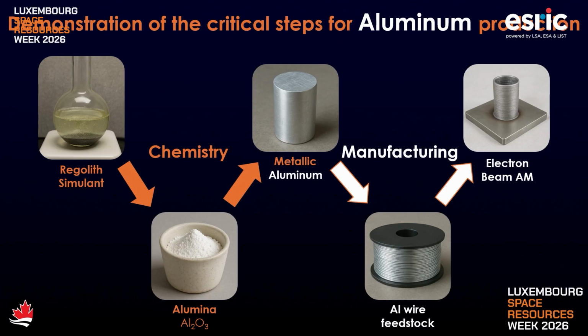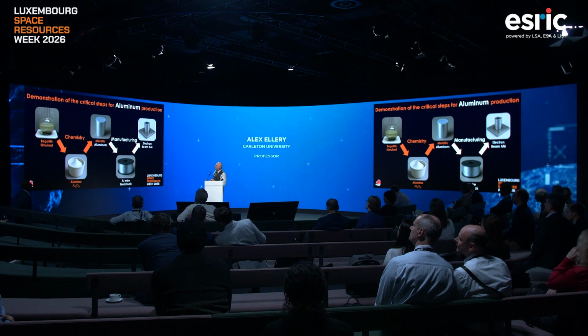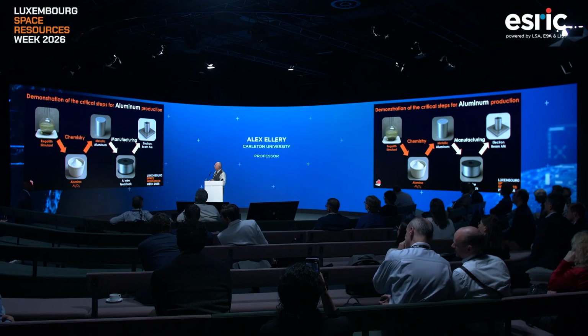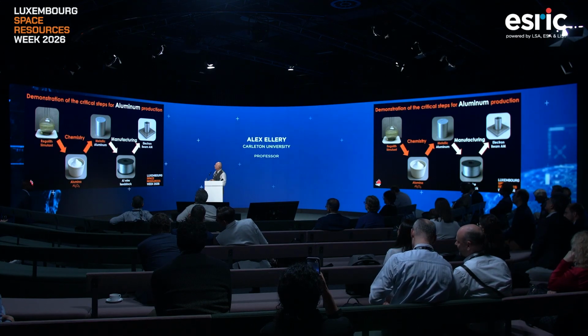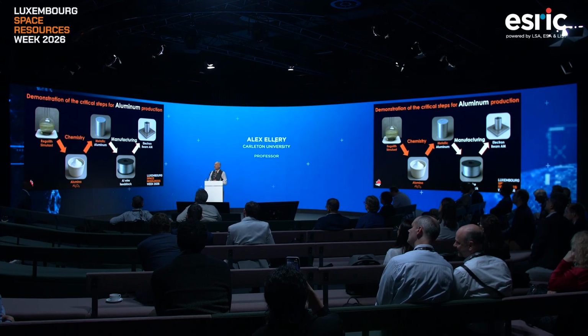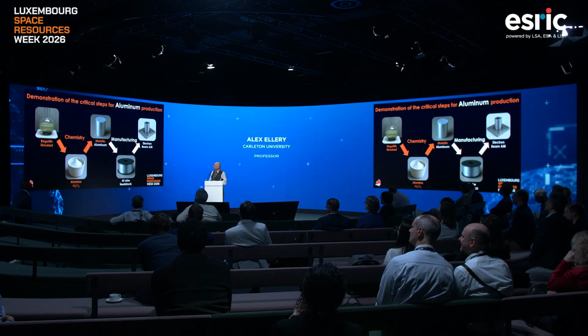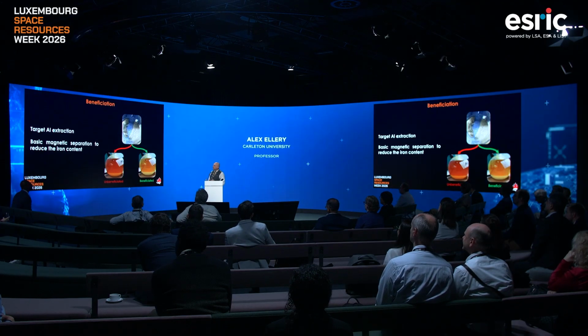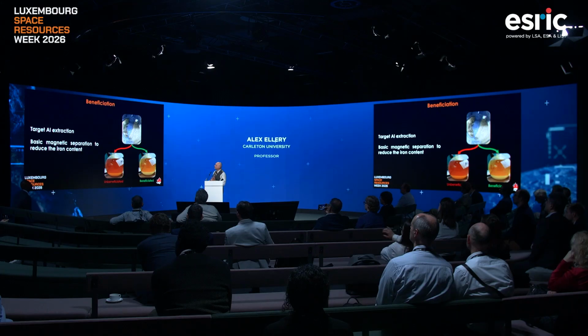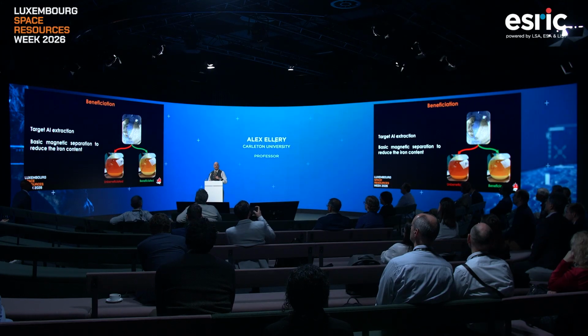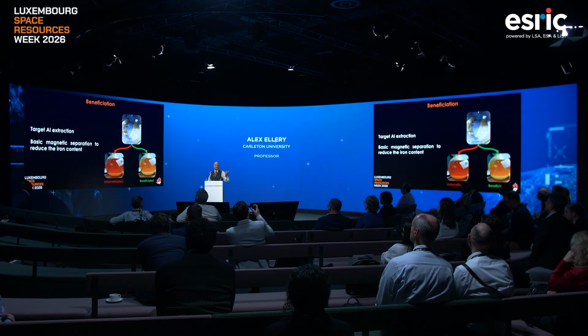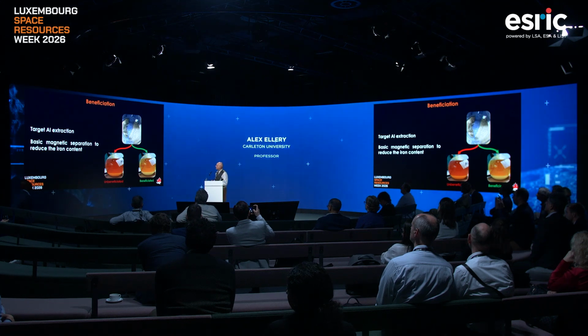So these are the critical steps. We started off with LHS-1, lunar simulant, and what we produced was alumina. This is actually the core process. We produced alumina, and then we reduced that into metal, and then drew that into wire feedstock, and then used electron beam additive manufacturing to produce structures. So we started off with the LHS-1, and the first thing we did was to separate out the iron component using magnets. Very, very simple, nothing terribly dramatic or sophisticated.